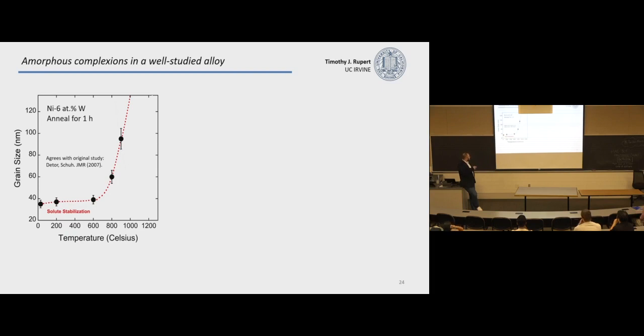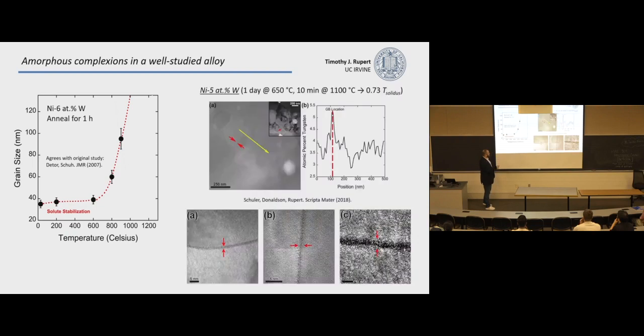This is the type of data you historically have seen. So the grain size versus annealing temperature. It stays stable until at some point it grows and goes away. Okay? Now, when we look at our predictions, we predict that amorphous grain boundaries should form up here. So we actually went and took this material, annealed it at these higher temperatures, looked at the grain boundaries, and we find examples of amorphous grain boundaries. They're not super thick. They're only about a nanometer, maybe a nanometer and a half, but you do see those